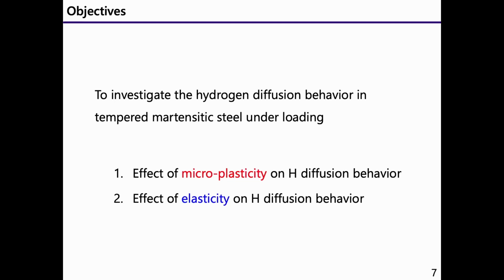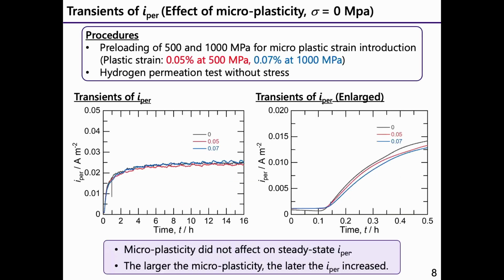Firstly, I would like to explain the result of the effect of microplasticity on hydrogen diffusion behavior. In order to investigate the effect of microplasticity on hydrogen diffusion behavior, firstly, we introduced microplastic strain in the steel by applying preloading of 500 and 1000 megapascal. The introduced plastic strain was 0.05% at 500 megapascal and 0.07% at 1000 megapascal. Then hydrogen permeation tests were conducted with various microplastic strain and without stress.